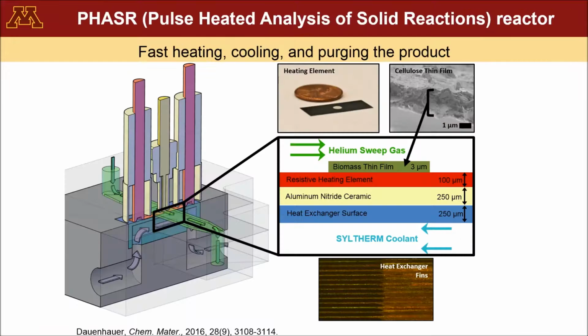This is what the Phasr reactor looks like inside. The Phasr is comprised of an upper heating block and a lower cooling part. And in the experiment, we apply current and voltage to rapidly heat the thin film sample. We use these two electrodes to apply current and voltage, and there is an optical pyrometer located directly above the sample that measures the temperature and feeds back to the controller to control the temperature. And there is also a Syltherm-based fluid flow below the sample in the heat exchanger that rapidly quenches the reaction.